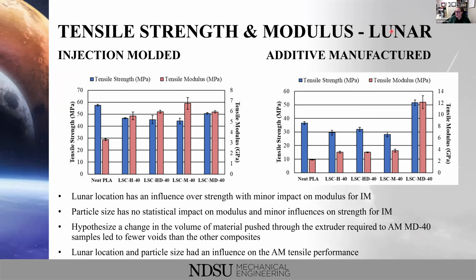We moved over to the lunar surface as well, and there's definitely an influence over the strength. There's a minor impact on the modulus for the injection molding in terms of the lunar location. There's really not a lot within these properties that was surprising to us. I think the biggest thing we didn't expect was that the particle size didn't really have an impact on the mechanical properties for the lunar composites. We very much expected that smaller particle size to have an influence over the strength and the modulus, but it really didn't.